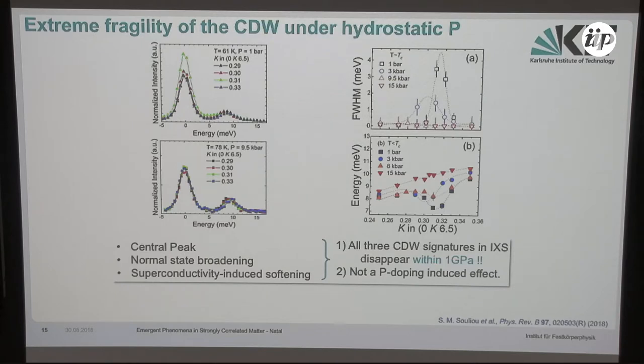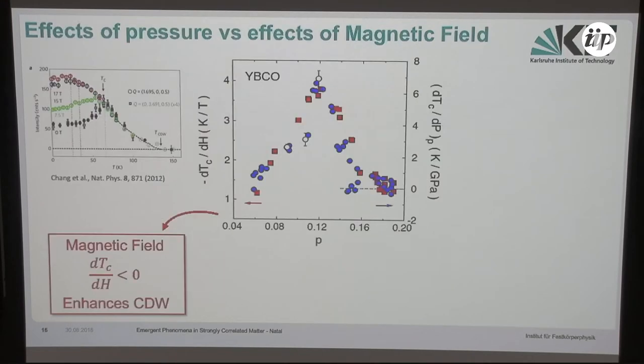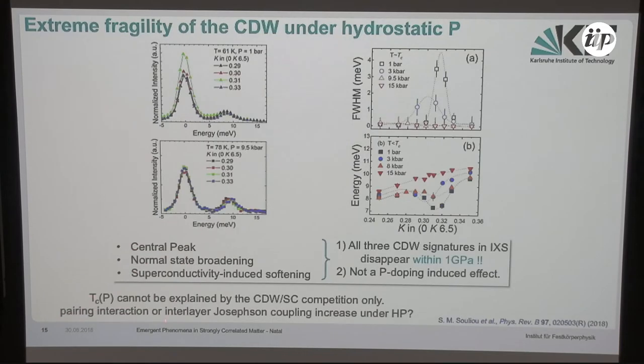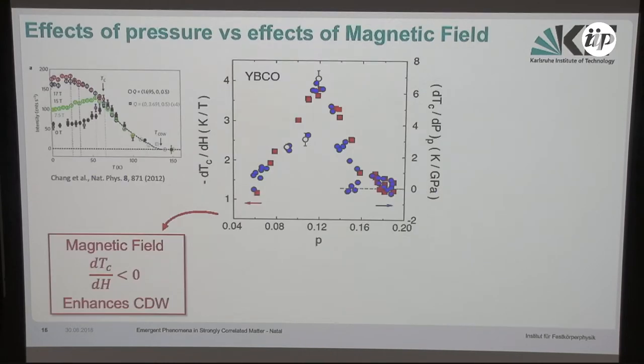I'm not going to discuss that too much, but we could check that the pressure-induced doping effect cannot explain this. So basically, there was at some point a tentative explanation that the very large increase of Tc, the dTc/dP that was seen, could be explained by the competition between the charge density wave and superconductivity, but I think it's useless because really the charge density wave is extremely fragile when you apply pressure. So there must be another explanation for that, and one probably needs to look in detail, finally after 30 years, at what happens to the crystalline structure when you apply pressure.